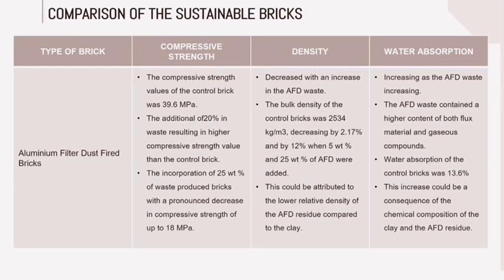So, the density of the aluminium filter dust fired brick decreased with an increase in the AFD waste. The bulk density of the control brick was 2534 kg/m³, decreasing by 2.17% and by 12% when 5% and 25% of AFD were added. This could be attributed to the lower relative density of the AFD residue compared to the clay.